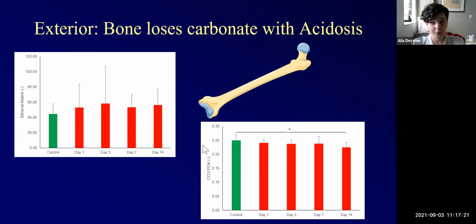So I told you the bone mineral is a calcium phosphate that has carbonate in it. So by measuring that carbonate to phosphate ratio, I can determine if there's changes in the amount of carbonate within the bone crystals itself. What you can see is that my mineral to matrix on the bone exterior is unchanged. I might have some dissolution, but it's pretty minor. I'm not really dissolving large amounts of crystals. However, at day 14, I have significantly reduced the amount of carbonate that is present in the bone mineral. So essentially, I've known that calcium is being taken out of the bone, but I'm also seeing that the carbonate is taken out of the bone.